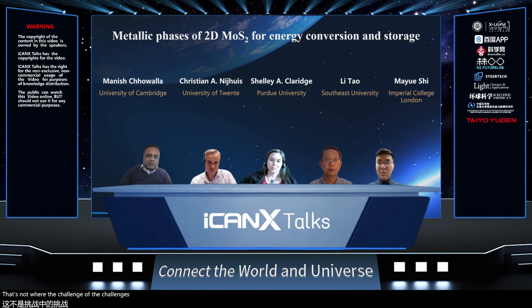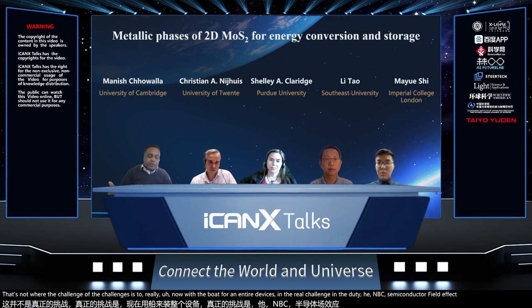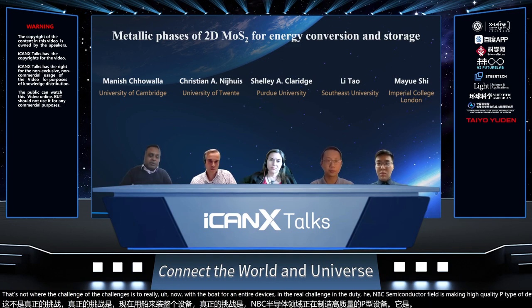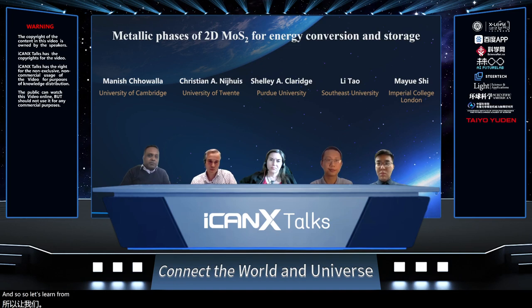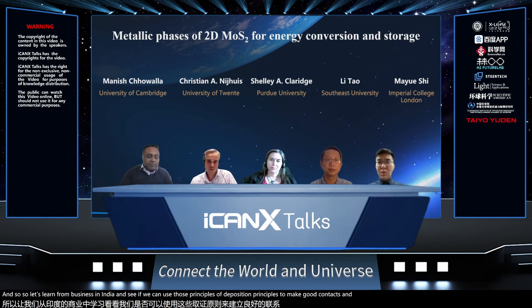The challenge is, because they both form N-type devices, that the real challenge in the 2D TMDC semiconductor field is making high quality P-type devices, right? And so let's learn from bismuth and indium and see if we can use those deposition principles to make good P-type contacts with platinum and palladium and other heavy metals. I think that is very interesting.